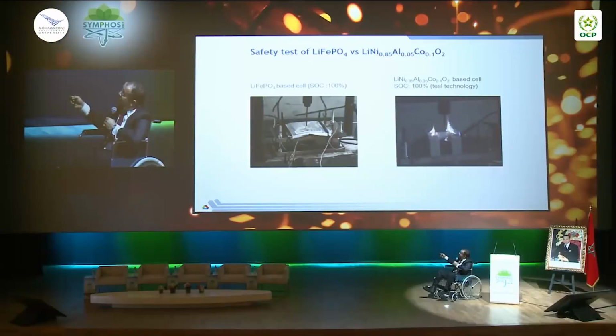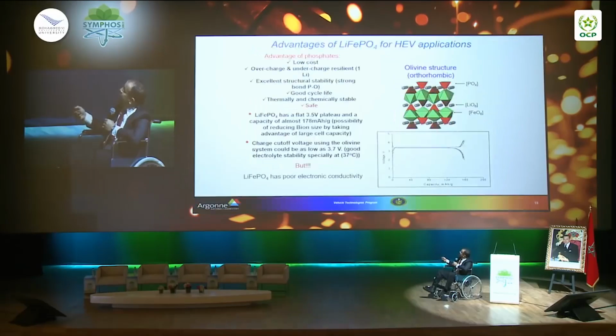And that's the reason why the Chinese are using this system, because of its outstanding safety characteristics. And one of the reasons is because the P-O bond is very difficult to break. So there is no oxygen release in this case. So it brings me to the iron phosphate. I'm going to mostly focus on the iron phosphate.